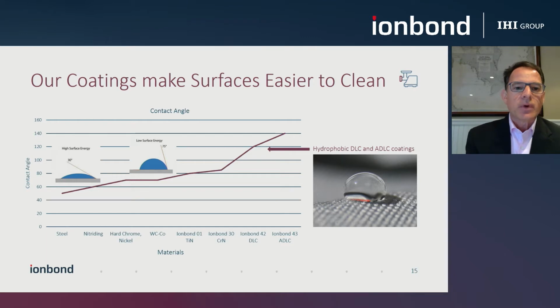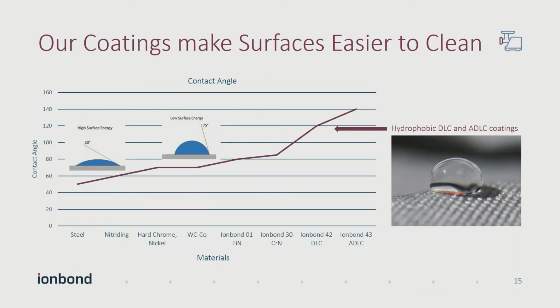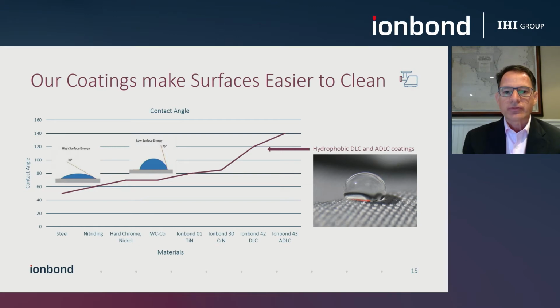In the next example, what we wanted to share with you is how our coatings make surfaces easier to clean. These coatings do have hydrophobic properties. What you're seeing in this graph is the contact angle on the left-hand side. Starting on the right-hand side and working to the left, the Ionbond 43 coating comes into play, 42. And as you can see, based on the properties of these different coatings, the surface contact angle changes, demonstrating the hydrophobic properties of these films.